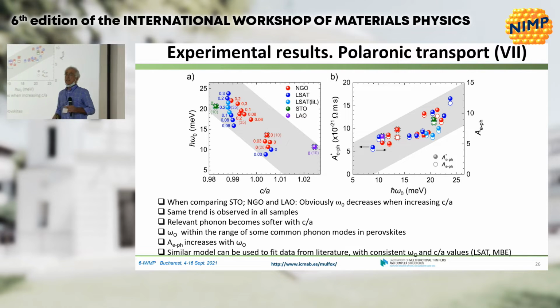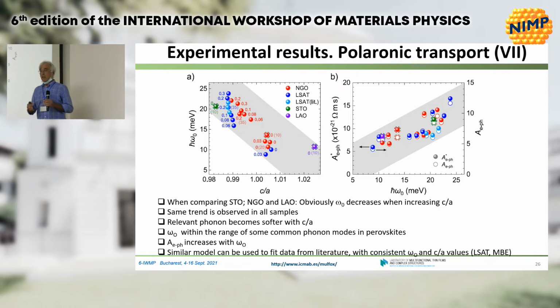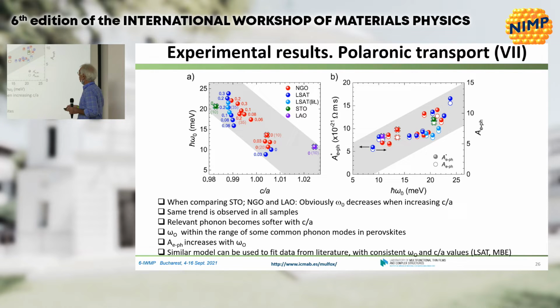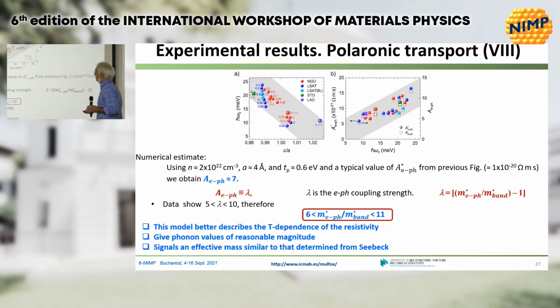So it seems that indeed omega 0, the frequency of the phonon, which is coupled apparently to the electrons, can be controlled by c/a, the distortion of the lattice. One can also determine the electron-phonon parameter, which is the prefactor, and this is the prefactor as extracted from the fit, and here transformed into a more convenient unit, but it's the same parameter. And from that, one can determine the effective mass of the carriers and the electron-phonon coupling parameter. And that is what you get.